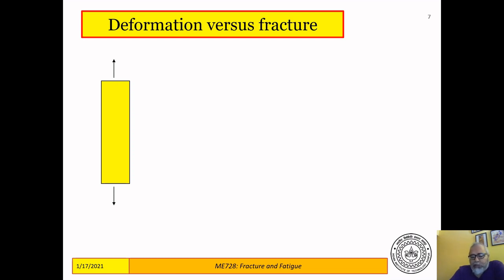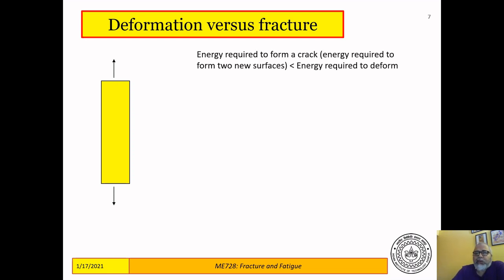Griffith suggested that this bar, instead of deforming, may form a crack if the energy required to form a crack is less than the energy required to deform it without forming a crack. Energy required to form a crack means a crack is two new surfaces that have to come up inside the material. Formation of these two new surfaces requires some energy. So, the energy required to form these two surfaces has to be less than the energy required to deform, in order that the crack can be formed.